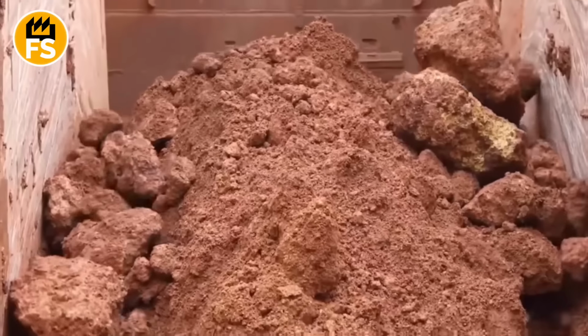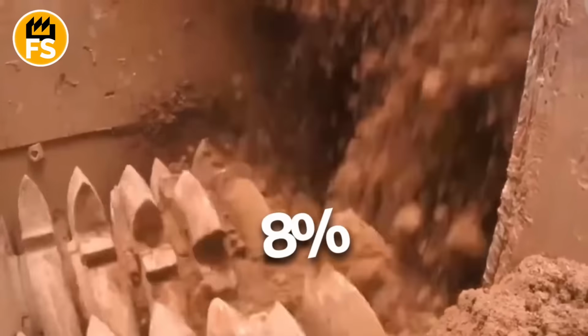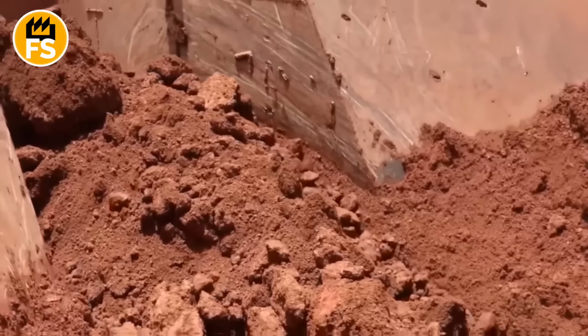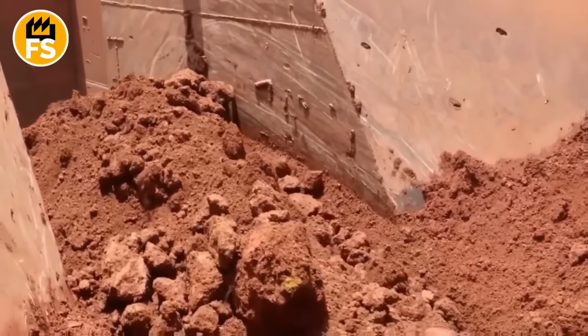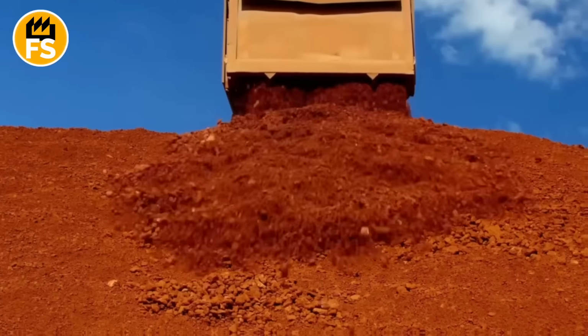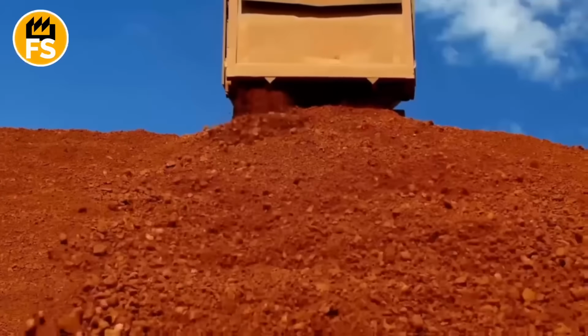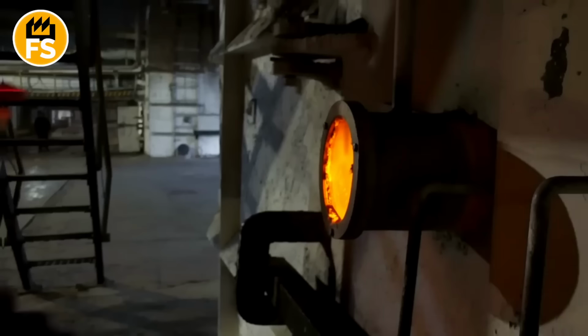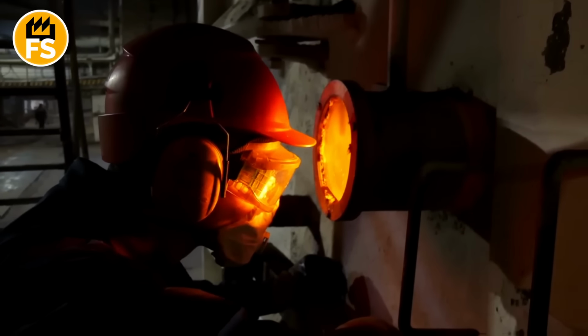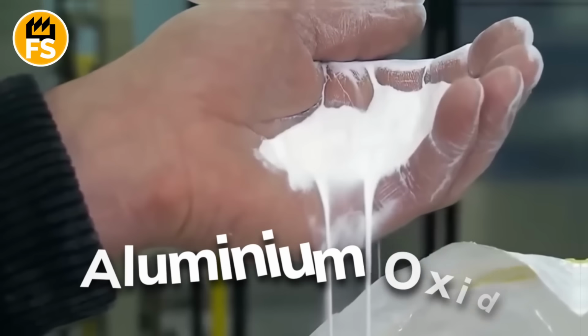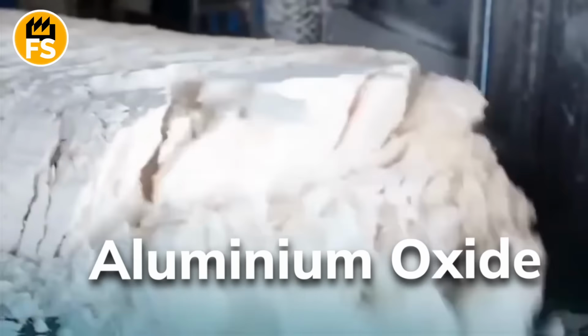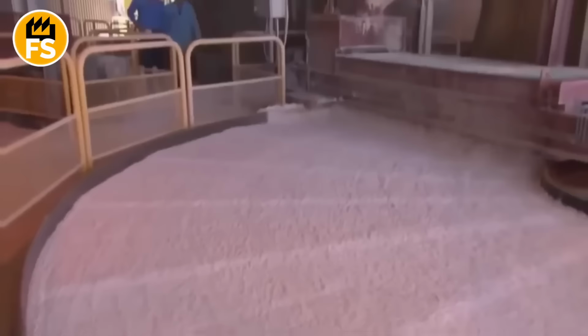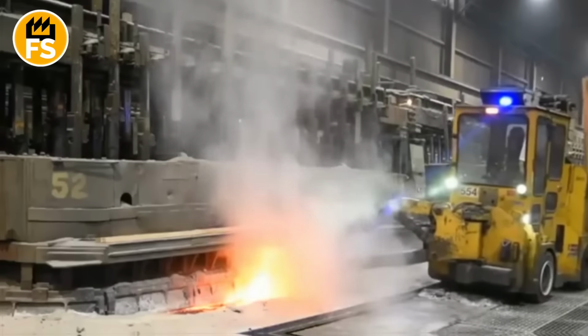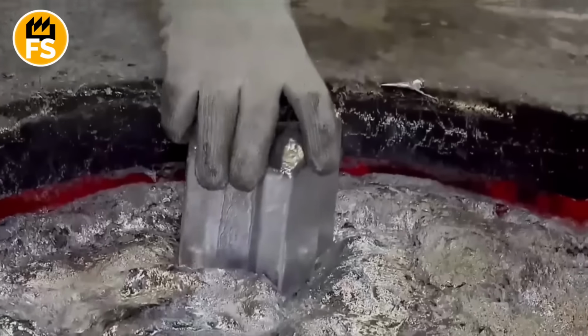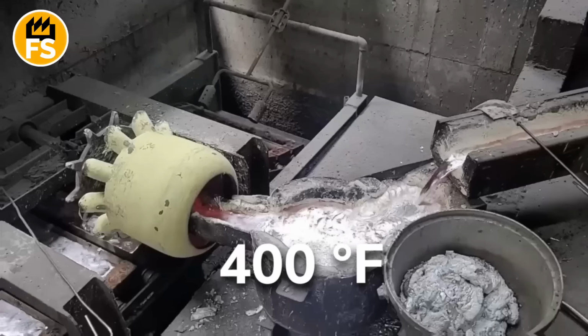It's the most abundant metal in Earth's crust, around 8%. But it's so tightly bound to oxygen that extracting it chemically is nearly impossible. Aluminum comes from bauxite, an ore containing aluminum hydroxide. First, bauxite gets treated with alkali under high temperature and pressure to produce pure aluminum oxide, alumina. Then this alumina gets melted through electrolysis in baths of molten cryolite at temperatures around 4,000 degrees Fahrenheit.